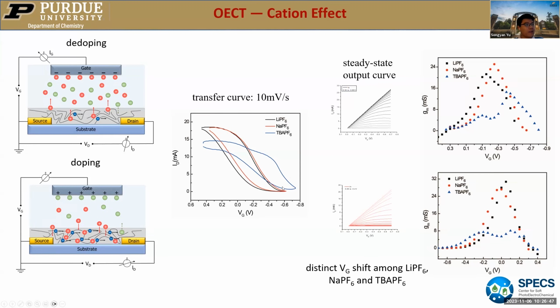And one thing for TBA PF6, we cannot really de-dope it to a very high level. I didn't do that because I found that if I want to completely de-dope the polymer, it will degrade and show very decayed performance. But for the other two electrolytes, it's okay. Then I also performed the output curve and converted the output curve to the transconductance plot. We can see clearly, this is for the de-doping process, this is for the doping process.